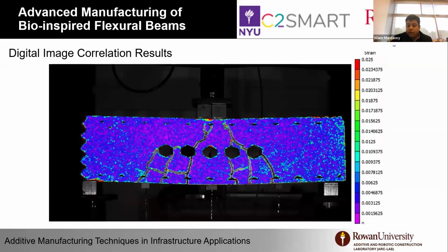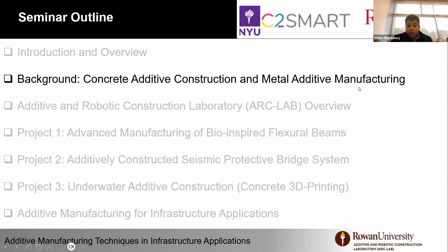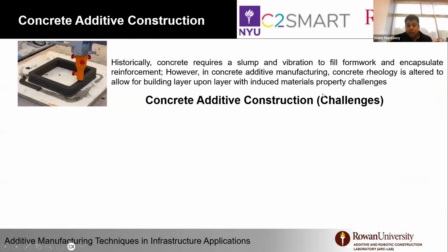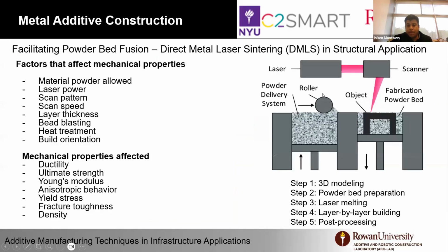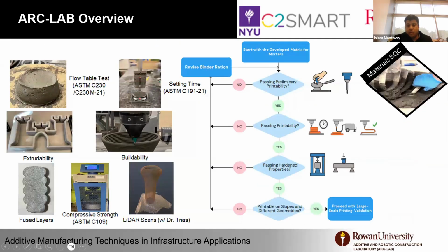So I have a slide early on that showed the process here, but I can show it quickly. You use flow tables similar to what you have in ultra high performance concrete, and setting times, and you're really using the equipment extensively to verify the extrusion and build up. This is our approach. There are also other approaches using rheometers and other techniques to quantify, but we are doing performance based always in our cases.